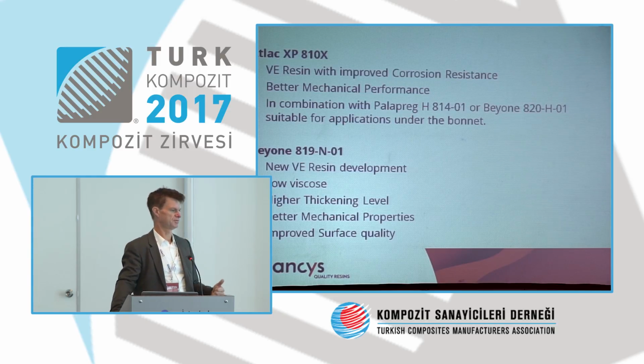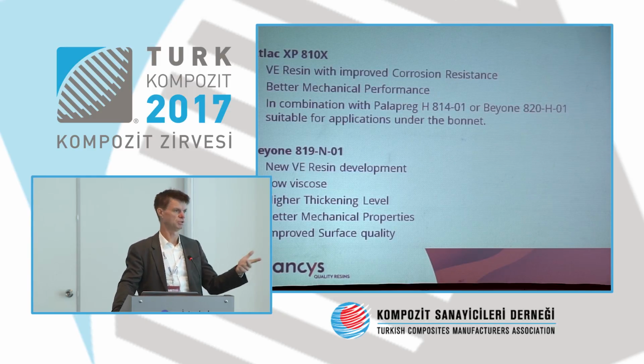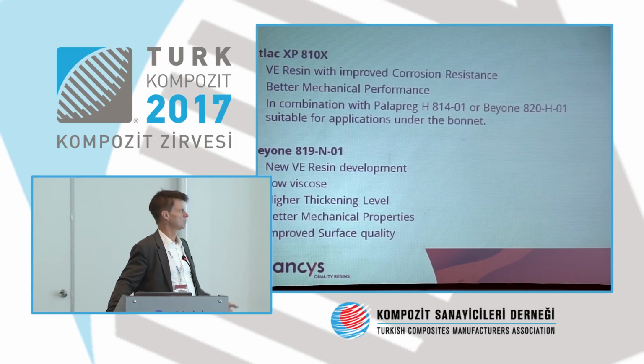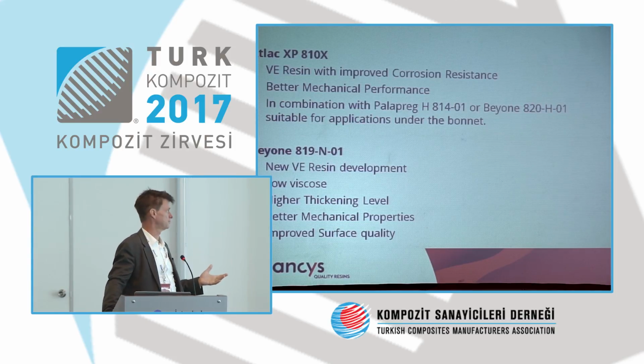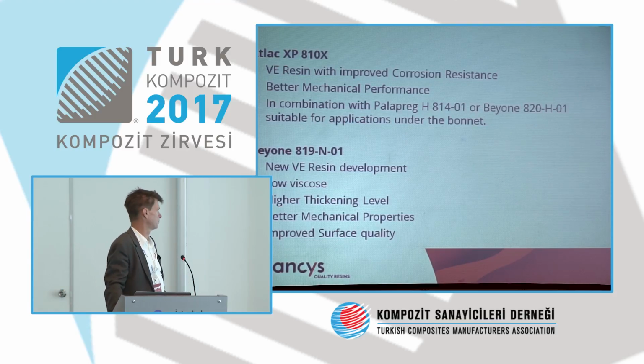Because in that area you have spray water, salt water, you have brake fluid, you have cleaning water. All these kind of elements, they impact this. And even oil. And oil can be also aggressive. So we've tested this, and the material is suitable. And for many years, it's already used in different trucks for heavy-duty trucks. And temperature resistant is also excellent, because everybody knows the temperature of oil within a car or within a truck can reach easily 90 degrees C. So, and this temperature will resist, no issues. So we have a lot of experience from the field, and this is still running.